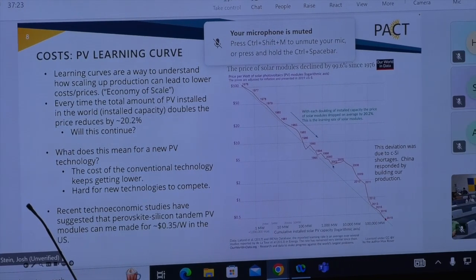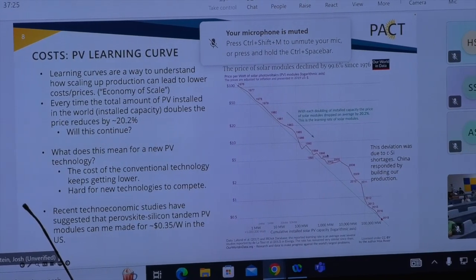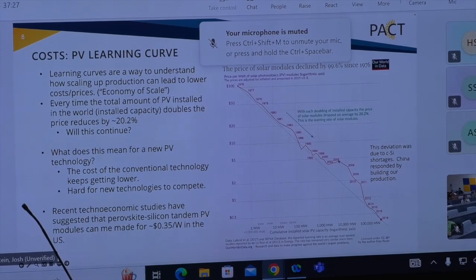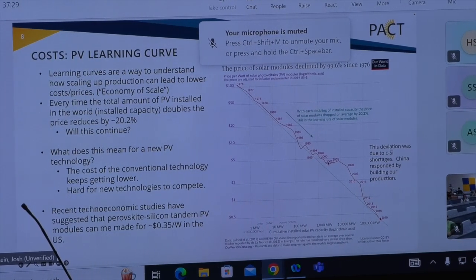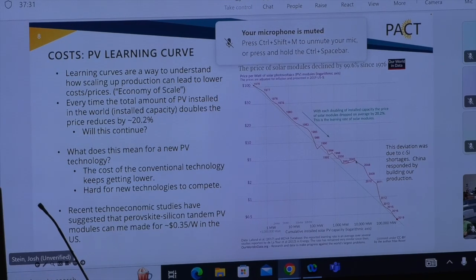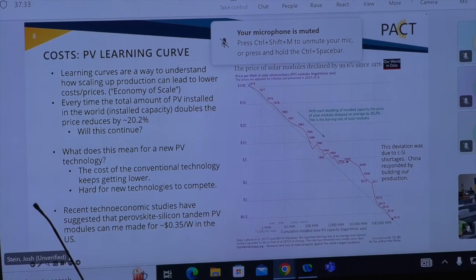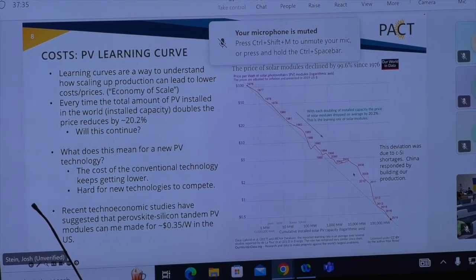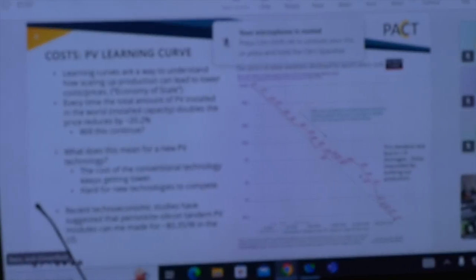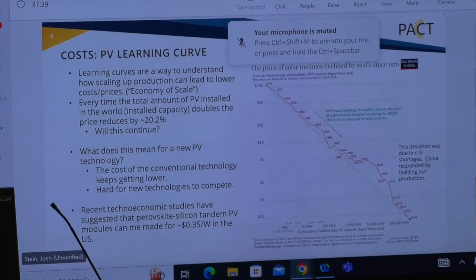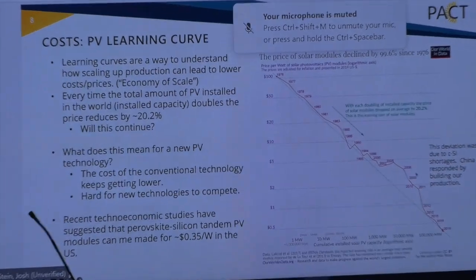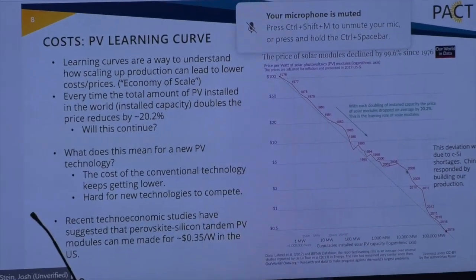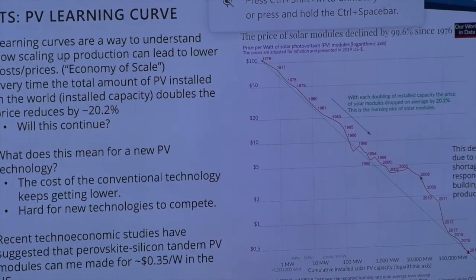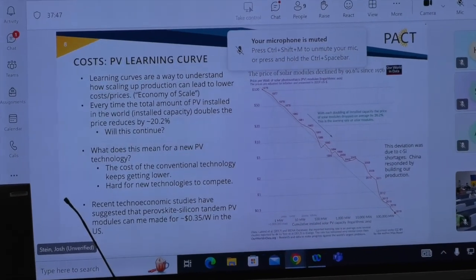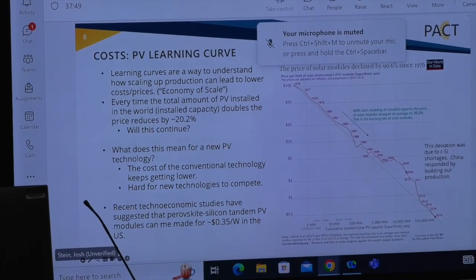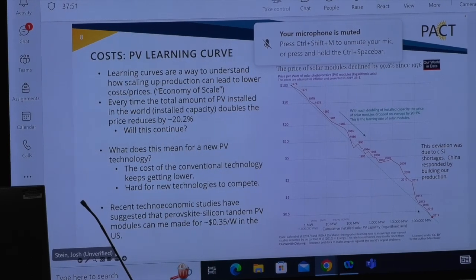There's an interesting deviation here that started around 2002, where the prices didn't get less expensive even with more production. This was a period where there was a shortage of the polysilicon material. And what happened is that China during this period responded by building huge capacity to have more polysilicon, and that then brought down the prices.